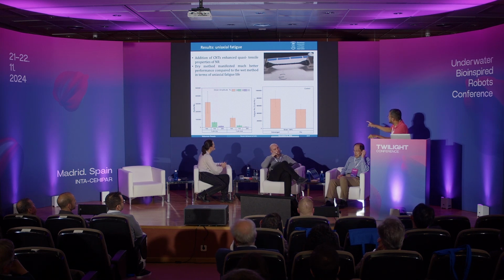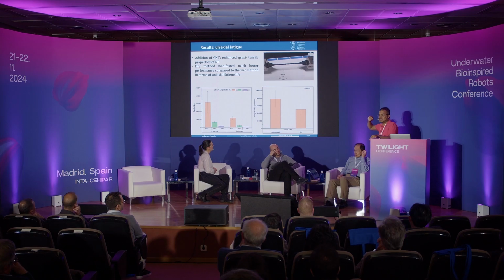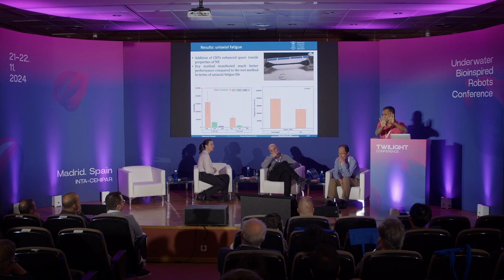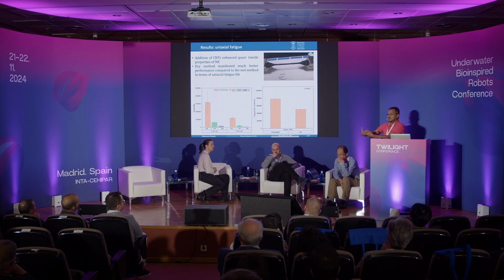And I found that the fatigue life in the submerged condition is much higher than in the dry condition. Please keep in mind, this is not about the synthesis. I do 2 types of synthesis, one is dry and one is wet, but I'm not talking about the synthesis technique. I'm talking about the testing condition. One is dry, one is wet. If it's wet, then you are getting higher fatigue life. That means if you do the fatigue in the sea, you will get higher fatigue life.